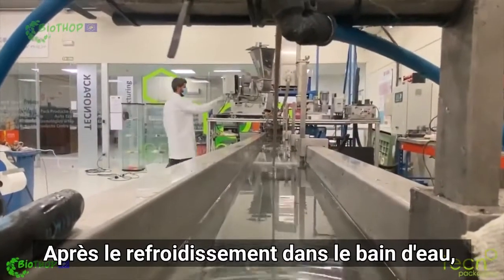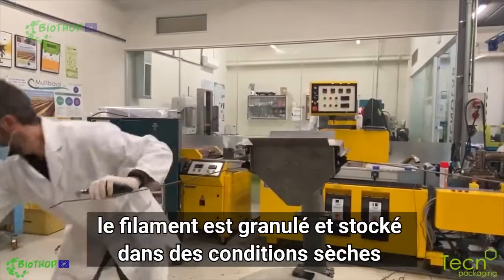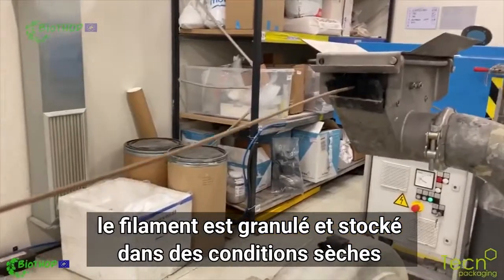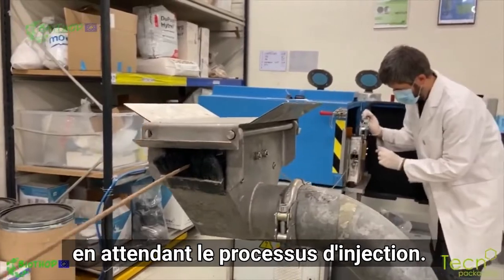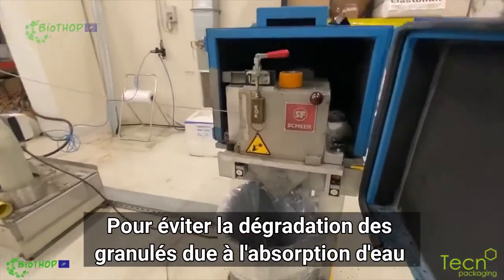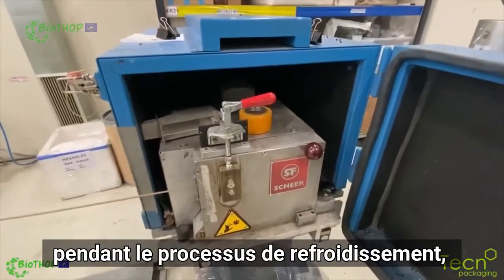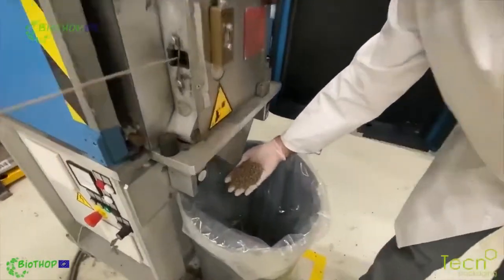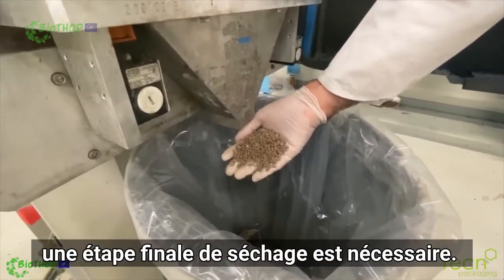After the cooling down in the water bath, the filament is pelletized and stored in dry conditions, waiting for the injection process to happen. To avoid the degradation of the pellets due to the absorption of water during the cooling down process, a final drying step is required.